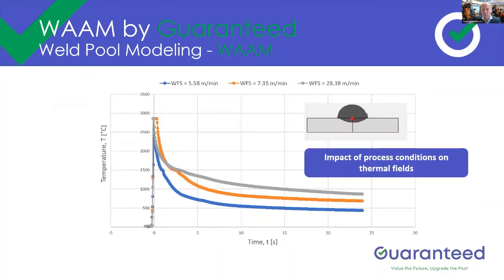And last but not least, we're also using it, of course, to look at what is the impact of the process conditions on the thermal fields. So you see an illustration here where we're actually plotting that transient behavior in a few points in the weld bead for different process conditions, to understand how the process conditions are going to influence the thermal behavior of the part, which is of course essential if you want to control things like distortion or warping of the component,